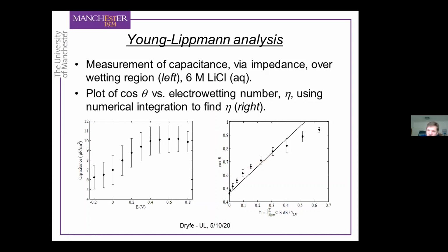Here is what we should see for the change in contact angle if the wetting effect were purely capacitively driven, and the dots are what we actually see. So the agreement isn't perfect. It's not too bad at low potentials, but you can see at higher potentials, the model isn't correct. So some parameter, perhaps the capacitance measurements, are out, because at higher potentials we see a lower change in contact angle than the theory would predict. So this is something that we're still working on.